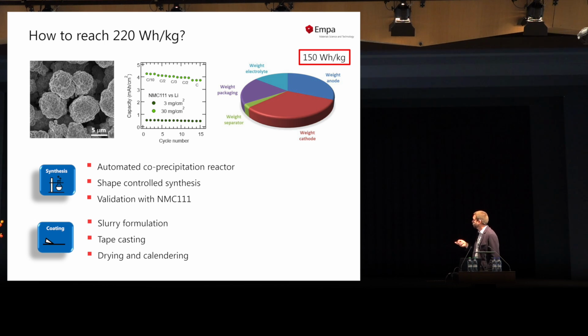But you can see here, we managed to have an initial areal charge capacity which is quite high, still in excess of 4 milliampere hours per square centimeter, and over 300 cycles some fading, which is also seen in the Panasonic cell, but which is quite okay, I think, for an academic cell. So with these improvements, we bring the energy density up to about 150 watt-hours per kilogram. This is still lower than the 220 watt-hours that we need to achieve.